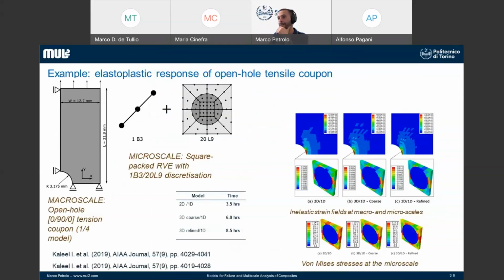Doing so, you can run this kind of analysis. So basically, you have the macro structure, in this case, a plate with a hole. You insert a macro load, for instance, tension, and then you build another model, so the RVE, and transfer the information from the macro scale to the micro scale. So you can get the stress field at the micro scale starting from the macro scale analysis. And on the right hand side of this slide, you can see a typical example of that. So you can see how the macro field on top is transferred to the micro field on the bottom.